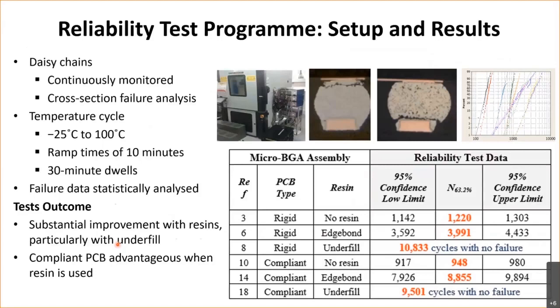Extensive reliability testing was undertaken on these components. What we could see was underfills are really good. You could see here, we're at nearly 11,000 cycles, still no failure. But with a rigid board with no resin, or a rigid board just with edge bond, much lower cycles to failure, characteristic life here. The compliant layer is good, particularly with underfills, and is reasonably good also with edge bond. That was a failure at 8,800 there. But just the compliant board without a resin doesn't really provide any benefits. You do need resins here, either edge bond or underfills.